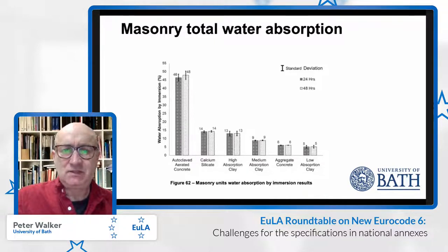And then total water absorption we established by immersion in water rather than the boil test or other tests. We just immersed in ambient water conditions in the laboratory for 24 and 48 hours. And in the main, we didn't see a great deal of difference between the 24 and 48 hour test. And the water absorption is a percentage of the dry weight of the masonry unit. So given the low density, high porosity of the AAC block, it's not surprising to see the high water absorption performance or value for those materials. And then we see with the other materials, they're ranging between 14 and 5%.